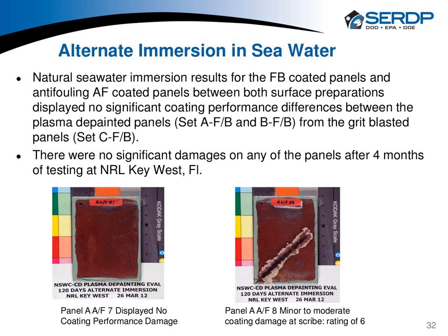Another very significant test that we undertook, which is as close as we could get to the real world, is alternate immersion in seawater. So this is where the panels, I forget the cycle, it might be twice a day, are dipped in seawater and then pulled out, similar to what a ship might see in the ocean. We did both, of course, anti-fouling and freeboard, and all of the ones above. The samples were scribed or unscribed, and the bottom line is, even after 4 months, there was no problem with any of these samples. We decided to let them cook even longer because we had already paid for this testing. And at the end of the tests, there were absolutely no problems.